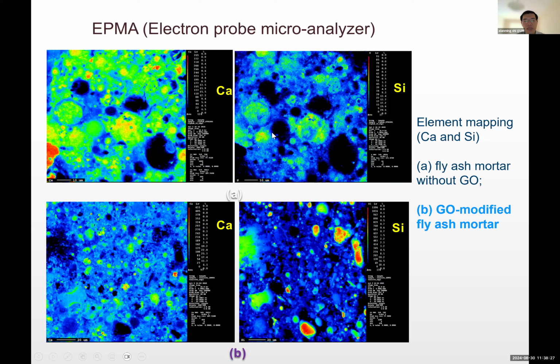So for instance, here you take a small cross-section of the concrete, or in this case, mortar, and then you select an area, let's say 100 by 100 microns, and then you scan it once, you get at least 5 or 6 different elements. Here we'll only show 2, which is calcium and silicate, but we would also be interested in sulfate, aluminum, iron, and so on. So this is a color map. The red color indicates a higher concentration. So these are actually digitized. So a 100 by 100 micron area would give you 500 pixels times 500 pixels. So it's tens of thousands of data points.